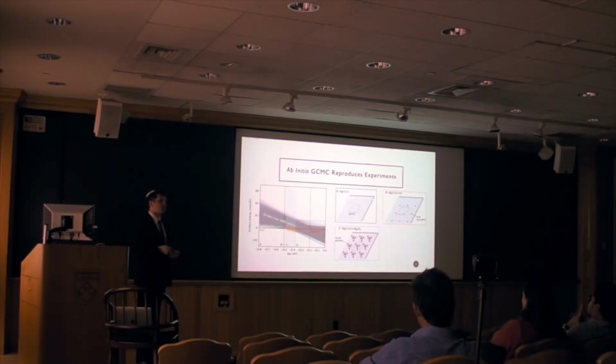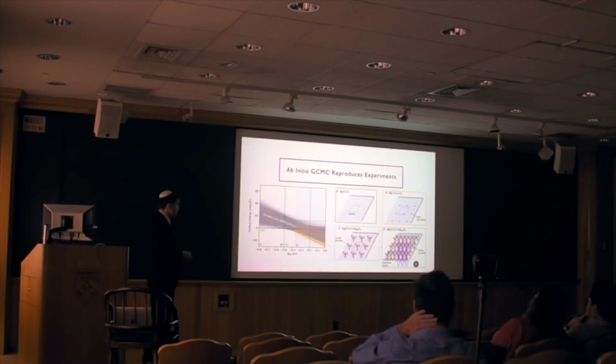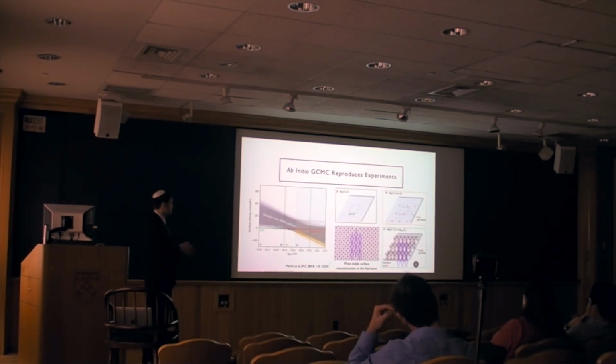If we increase the oxygen pressure even further to the highest pressure regime, what we find is that the Ag3O4 pyramids become distorted first. And also you can see that they start to dimerize, and that's highlighted here by these purple diamonds. And this particular arrangement of connected diamonds is very close to what they see in the literature. The only difference being that these connected diamond chains are shifted by a small amount in this vertical direction.